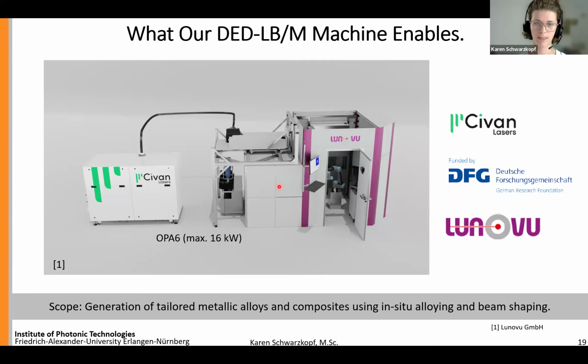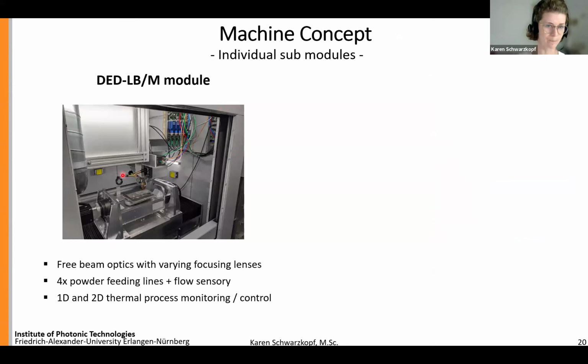And this cell looks, if you're now looking inside it, like this. What you can see here is, at first glance, the processing head, where all the powder is gathered into the material or the substrate surface. The powder itself is directed from these powder feeders here. We have 4 of them, which allows us to combine 4 different powder mixtures in the process zone. What we also have are different approaches to really measure the temperature, but also the surface roughness of our process. And in general, we can say that we have different focal lengths that allow us to steer the beam shape size.